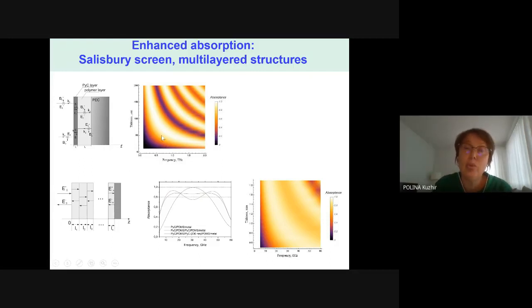With this, we could achieve perfect electromagnetic absorption at many thicknesses of this material, corresponding to odd numbers of quarter wavelengths. If you don't want perfect absorption but want broadband absorption, maybe not as perfect but still high,